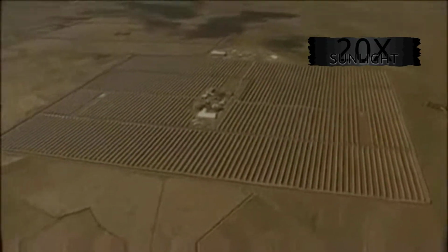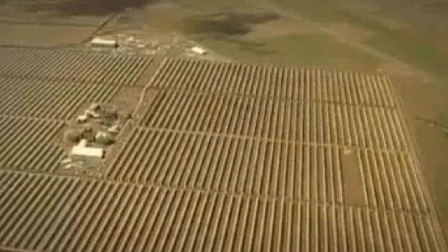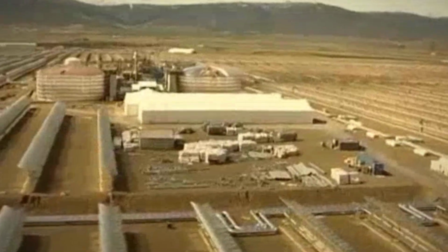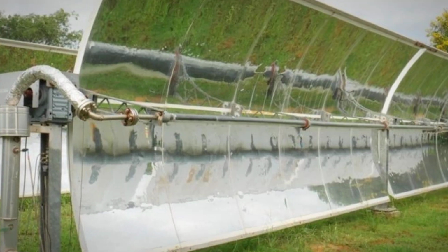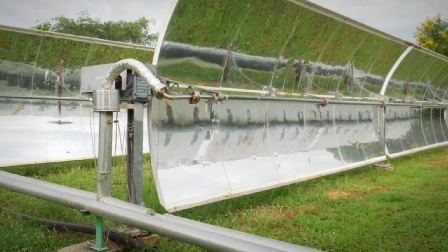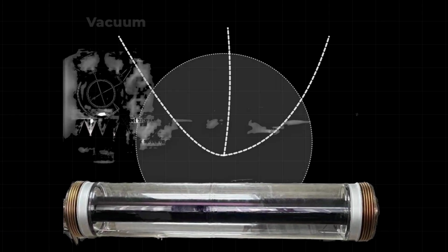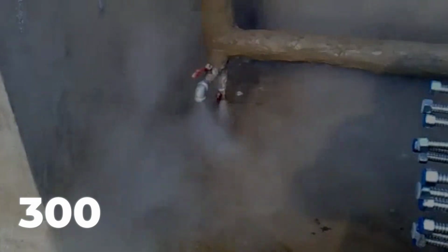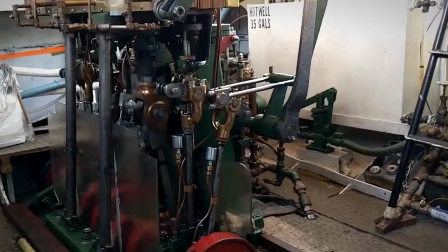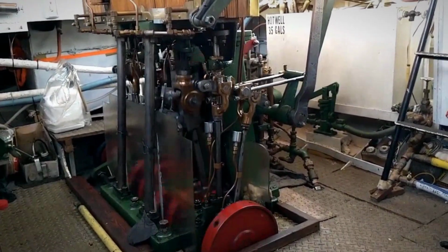The real magic is in the numbers. With a concentration ratio of 10 to 20 times, the trough gathers the energy of a dozen square meters of sunlight and funnels it onto a pipe barely an inch wide. The result is that the fluid inside the receiver can reach temperatures above 300 degrees Celsius, hot enough to boil water for steam engines or drive absorption chillers.